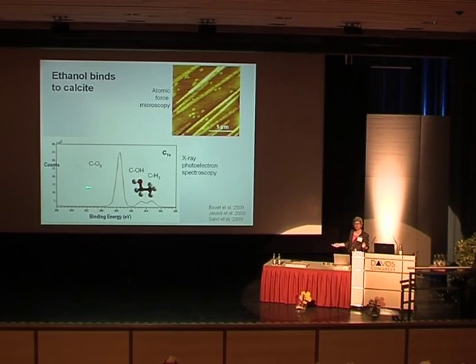We looked at it with X-ray photoelectron spectroscopy. Now this is a technique that collects information from the very top, the top few nanometers only. And so it's very surface sensitive. So on the surface of our calcite, we can see the ethanol as these two little peaks. This is the carbonate peak, the peak for carbon stuck to oxygen. And these are the peaks for carbon stuck to OH and carbon stuck to just H's or itself, carbon-carbon. So we can see ethanol there on the surface.